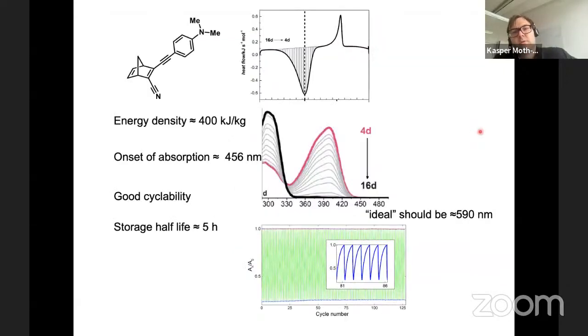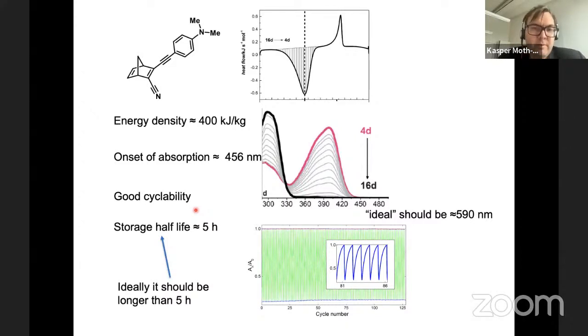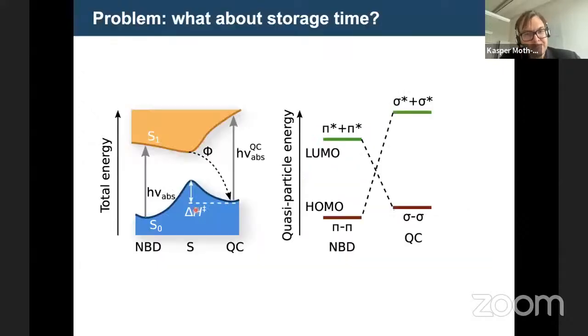So this system had good energy storage density and very nice optical properties. You see here's a picture. The pink one is the absorption spectrum of the norbornadiene, and the black curve is the quadricyclane. It's almost fully transparent, and we can cycle it many times. Still, we want to have better absorption properties, and the storage half-life of 5 hours is not really enough. It should be more than 5 hours. I mean, imagine if you had a cell phone and it lost all its charging in 5 hours, it would not really be useful. So we have to work with that.